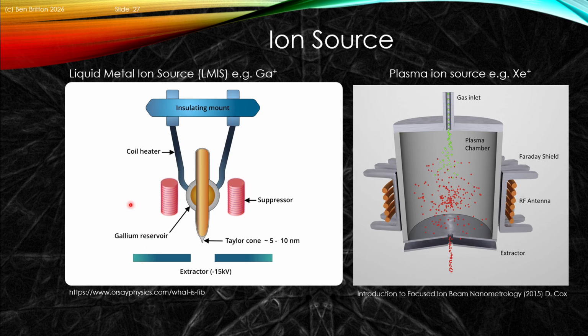Now, if we look at our sources, this is where there's just the subtlety of the two different source types. Let's focus on the left hand. This is the liquid metal ion source. Basically, we have a tungsten hairpin coil, and we have a gallium reservoir, and that gallium reservoir enables us to effectively wet the end of our tungsten hairpin. So we can basically have this wet.